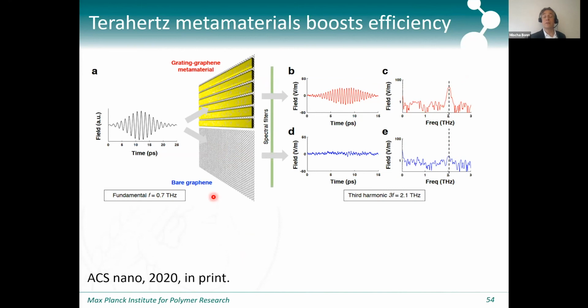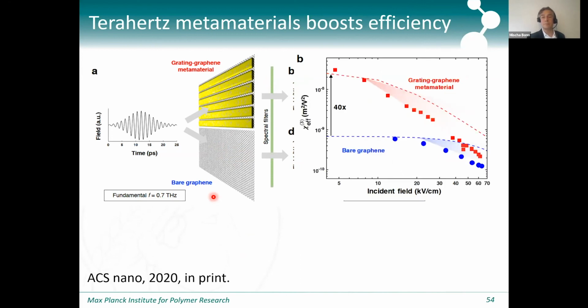And so this is a nice way of using the graphene nonlinearity with tabletop, very simple laser systems. You can see that at very low field strength, you can get an enhancement of up to a factor of 40 compared to the bare graphene.